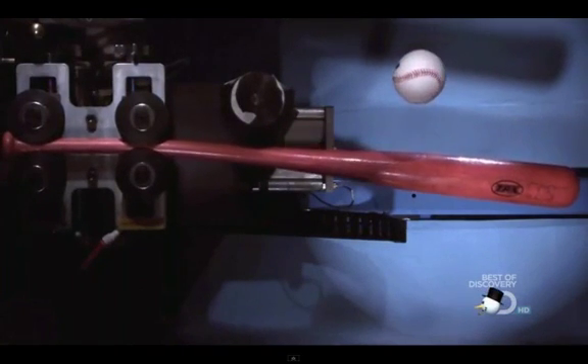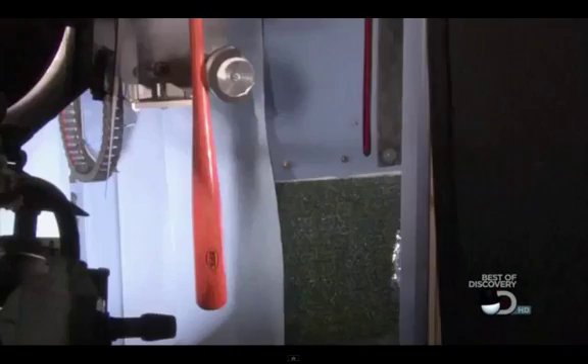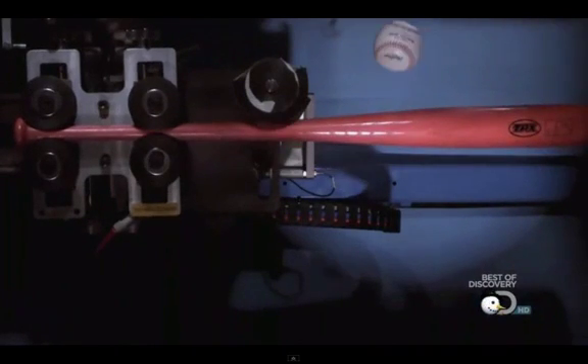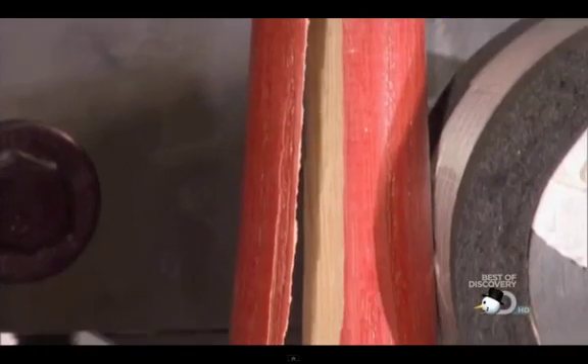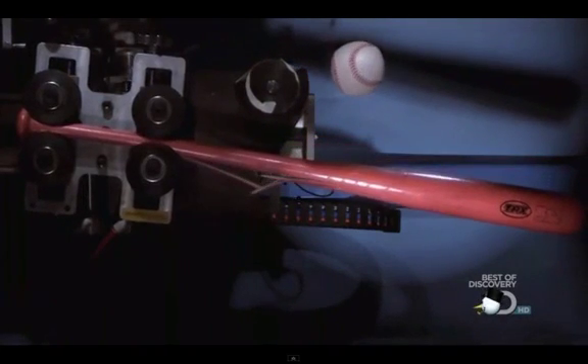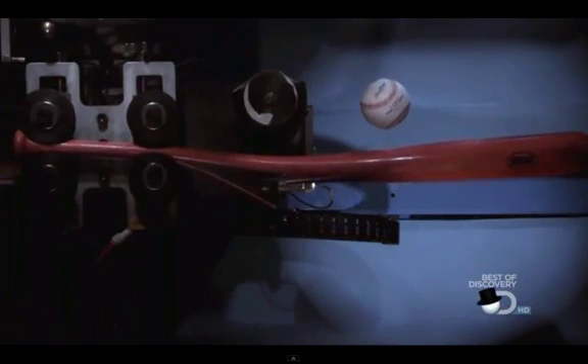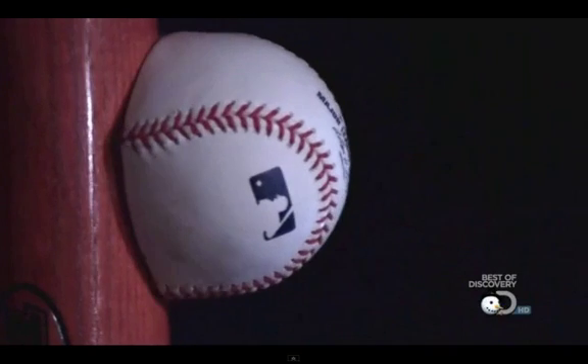And what if we move it just a bit further? Can we create that bat-breaking surprise? The bat is broken. You can really see when the bat starts to break, all of the energy of the ball has gone into breaking the bat. It's much more common that the bat splinters a little bit than to actually split apart. Just as the ball is making full contact, we're seeing the bat starting to break. It's not that the ball is harder than the bat — far from it. But when a batter misses the sweet spot, the force of the ball makes the bat vibrate and bend so violently that it splits at the weakest point, often along the grain.